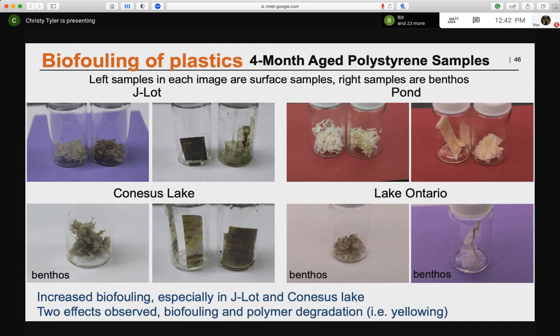For instance, if we look at the samples from the pond, you can see this yellowing and clouding occurring. This is indicative of some oxidation occurring of these films as well. So we can think about both chemical changes along with these physical changes. The increasing of these biofilms will probably change their densities, which is why we're looking at the settling. If you increase its density, it's going to settle more. So even if you start out with a plastic that was less dense than water, it could eventually still settle out.